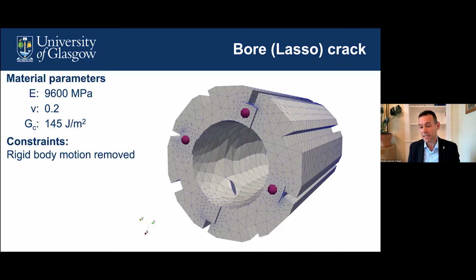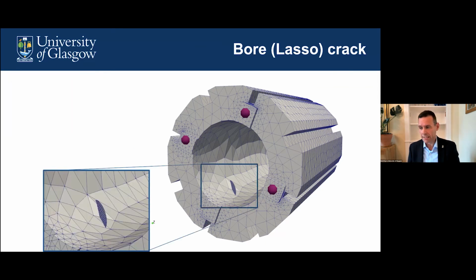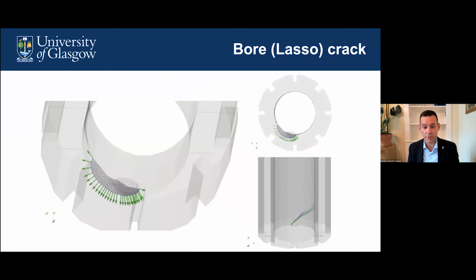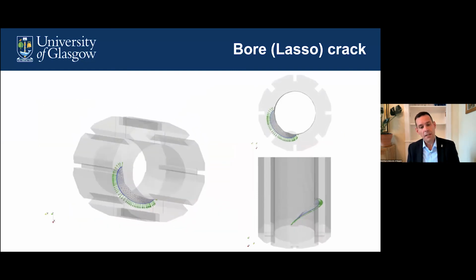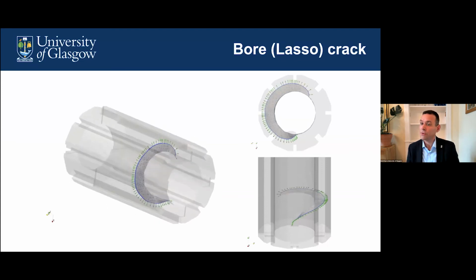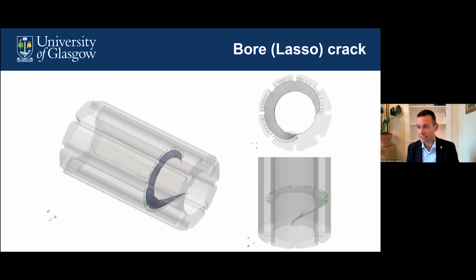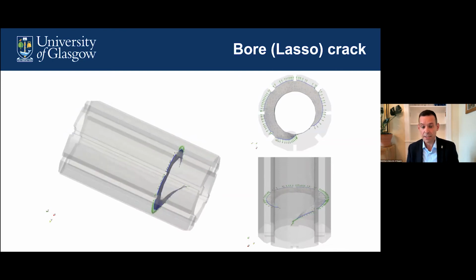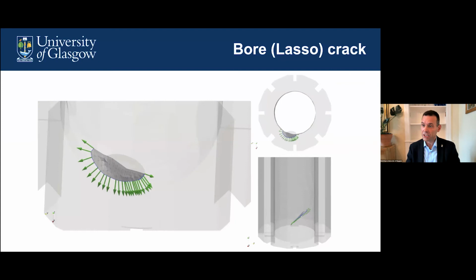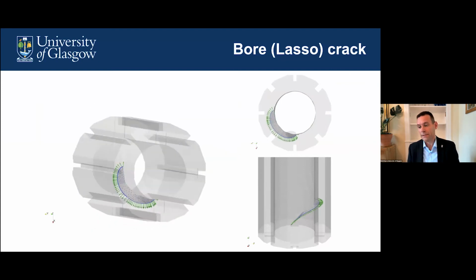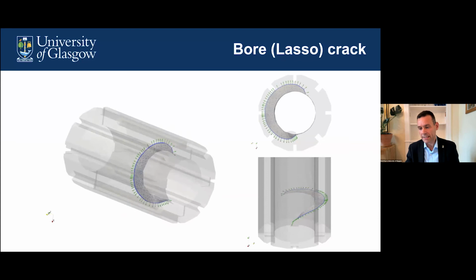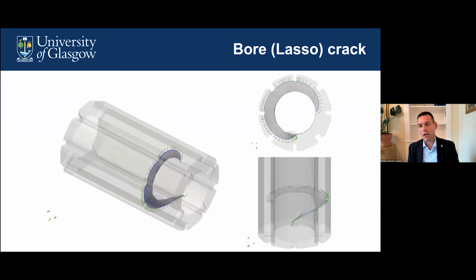And another example here is where we have a so-called bore crack, where the crack is seated on the internal surface of the brick. Again, rigid body motion is removed, and we then run an analysis due to the internal stress state that is predicted as a result of aging. And you can see here the crack propagates in a kind of circumferential manner. This is a very difficult analysis because you've got a very, very long crack front with lots of parts interacting with the free surface of the brick. So you see the crack continuously propagating in a circumferential direction around the brick.